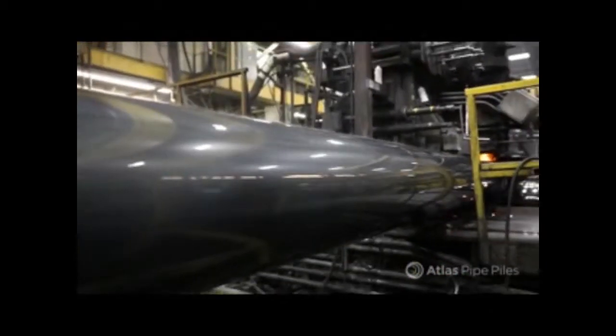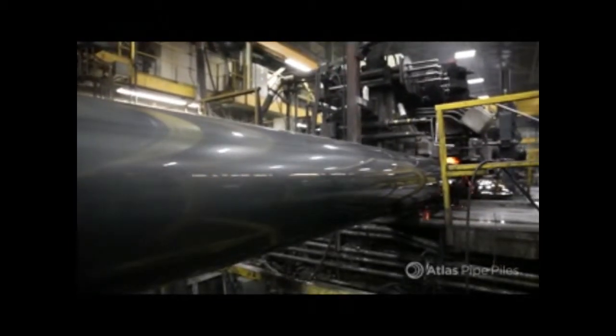Atlas straight-seamed pipe piles are welded utilizing electric resistance welding. Abbreviated as ERW, this welding process utilizes 2 copper contact shoes to pass electrical current through the strip edges of the coil. Resistance to that flow of electricity causes heat to build up in the strip. The heat zone can reach 2,700 degrees Fahrenheit, all while the line is running at speeds of up to 120 feet per minute. The result is a continuous longitudinal weld with pinpoint accuracy, and the pipe is ready for finishing.